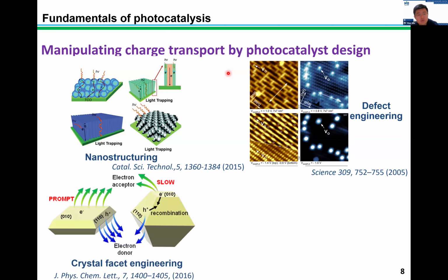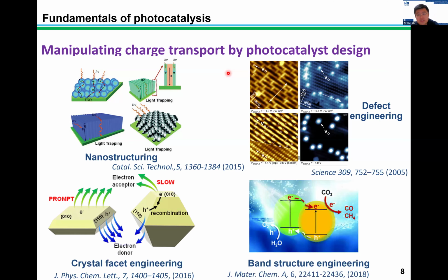Certainly, we are also interested in crystal facet engineering. We can synthesize our catalyst with identical composition and crystallinity, but just with different facet ratios. In this situation, we can promote the charge separation spatially and also steer the reaction toward our desired products. Lastly, we are also interested in designing and fabricating heterostructured composites with two or even three photoactive semiconductors combined together, taking advantage of their redox potentials and light absorption with facilitated interfacial charge separation.